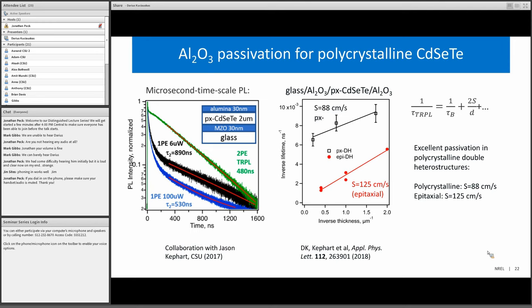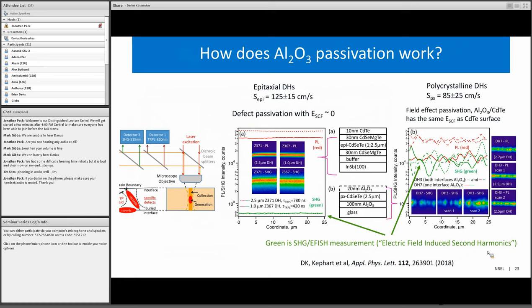But the question, though, is how does it work? And these second harmonic measurements, correlated electric field-induced second harmonic measurements, are very informative in this regard. Because if we look at the passivation for the epitaxial and polycrystalline samples, they have similar recombination velocities, but they appear to have different mechanisms. So the E-FISH signal is very weak in the epitaxial sample, in which passivation is made by epitaxial growth of the lattice match material. In that case, the interface defects and charges are passivated, and there is no near-interface electric field. So the green signal is very weak.